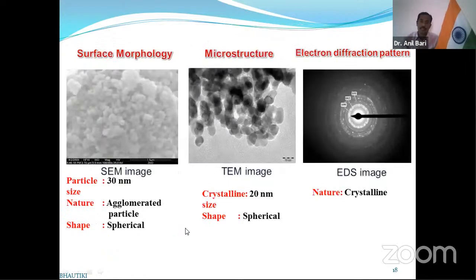Then this powder is further characterized: surface morphology with the help of SEM, microstructure with the help of TEM, and electron diffraction pattern with the help of EDS image. From the surface morphology, the particle size is observed to be 30 nanometers, having agglomerated particles, and the shape should be spherical. Then from transmission electron microscopy, the crystallite size should be 20 nanometers, spherical in shape. And the electron diffraction pattern shows the crystalline nature of the prepared nanostructure powder.